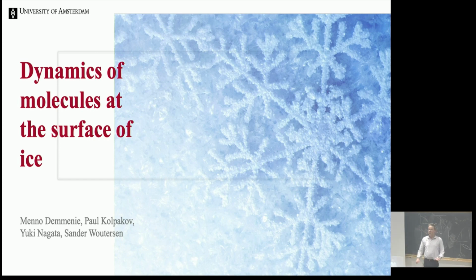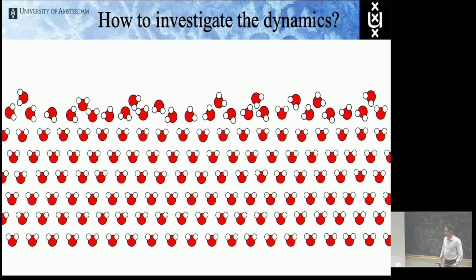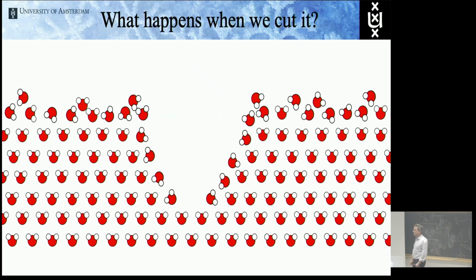And together with Menno, who's still awake, that's good, we actually found a very cute way of doing that, if I say so myself. So this is what the ice surface could look like. There may be a little bit of roughness, and there may be a little bit of disorder close to the surface. But what would happen if we would cut it? If the two ice spheres of Kingery sinter, this scratch would probably fill up. And the way that it fills up would probably tell us what the mechanism is. That's what we're going to do.